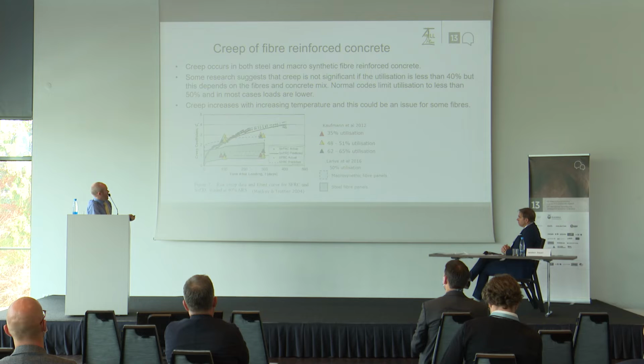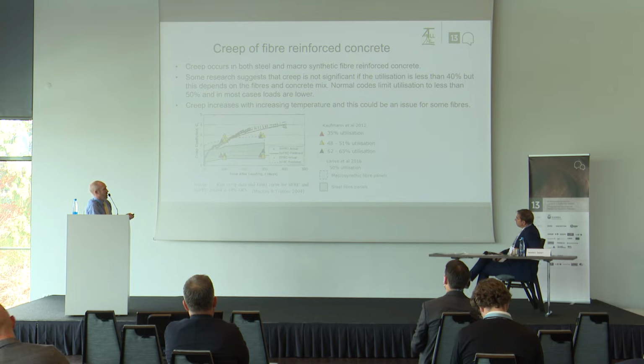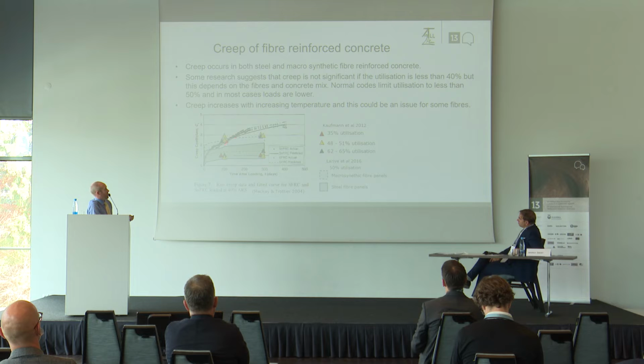If we're at that sort of normal working level, they're generally creeping in a little bit more, maybe 1.5 times, but it's not the same order. The triangles are, again, macrosynthetic fibers, so they're in the same range. And then the third study, at a utilization of 40%, they actually found, if you look at these dots, that the steel fibers on that occasion performed in the same way as the macrosynthetic.